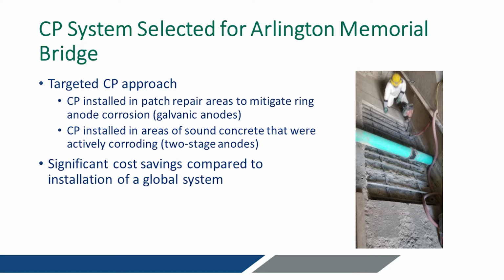You don't have external electronics anymore from an impressed current system, and you can install fewer anodes than you normally would with a purely galvanic system. Another thing we want to do on the project is this is a rather large structure, right? We don't need to put cathodic protection on every square inch of this structure. Not every square inch is deteriorating. So really using the investigation that we identified at the beginning with the chlorides and the corrosion potential survey, we identify where there is active corrosion and install these in a targeted method to prevent corrosion in those areas.